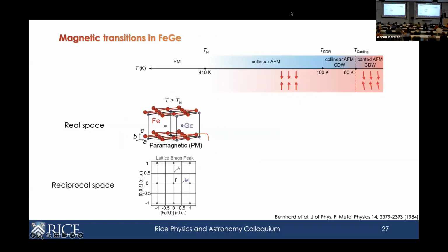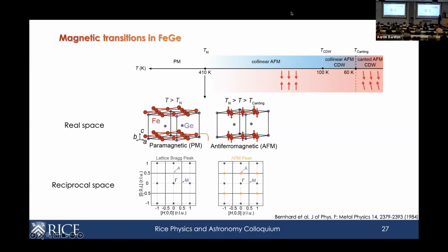So iron germanium is structurally very simple. It's been around for a very long time, almost 40 years. And what was known about it before is that if you look at the crystal structure, the red balls are the iron, and they make these Kagome lattices, stacked along the c-axis, right? So it was known already that below 410 Kelvin, the moments become ordered on the iron lattice. They're ordered such that they all point in the same way within one sheet, and then they all flip over on the next sheet, and then this repeats, right?